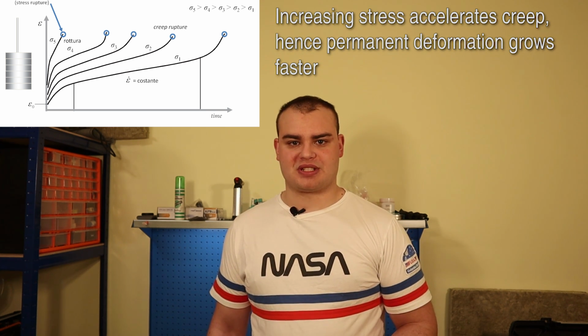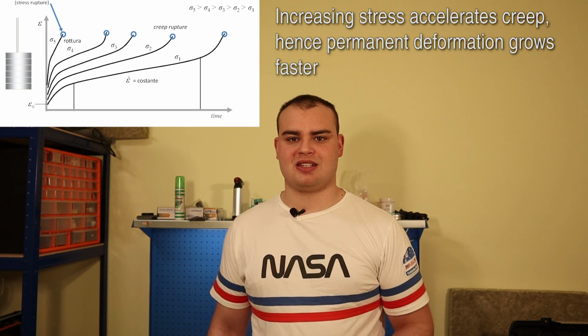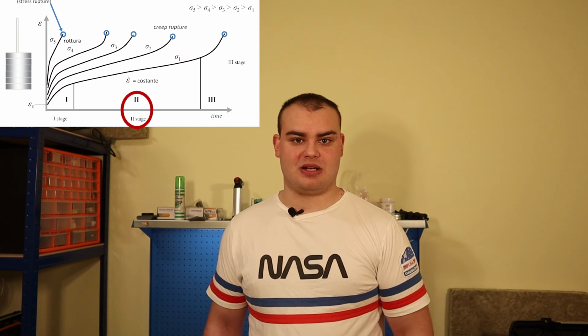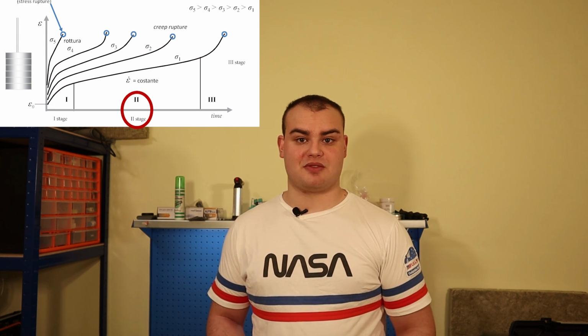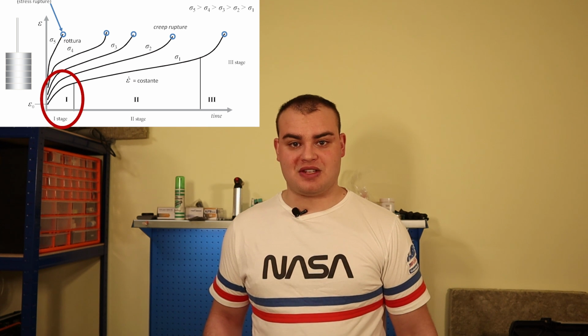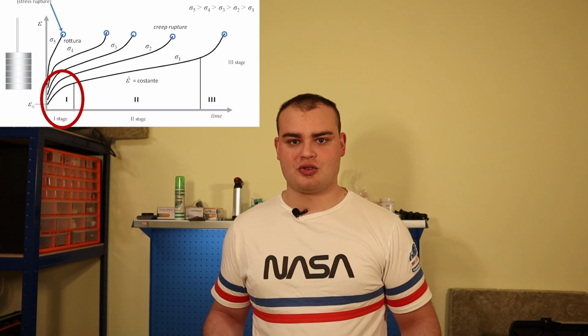But second and most importantly, even though at room temperature the relaxation or creep rate is so slow to be usually negligible, that relates to steady state creep, also known as second phase creep. That occupies by far the longest part of the component's life, and that's why it is considered to be the most important, especially at high temperatures. However, a first phase also exists, during which the rate of deformation is much higher, but that usually doesn't last very long.